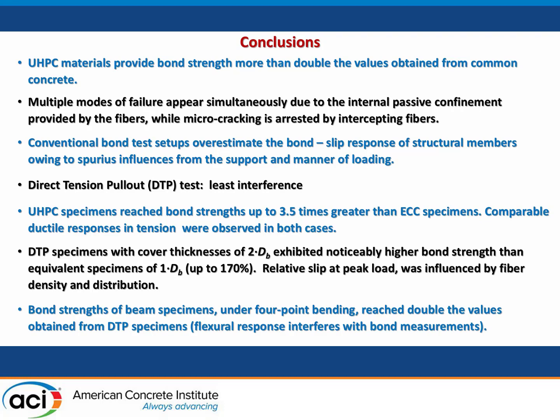Conventional bond test setups generally led to an overestimation of the bond slip response of structural members. This is owing to the spurious influence of either the specimen form or the manner of loading. The direct tension pullout test proved to be the most conservative, leading to the least possible interference. The UHPC specimens reached bond strengths that were as high as 3.5 times greater than the ECC specimens, and both responses were very ductile in terms of slip.